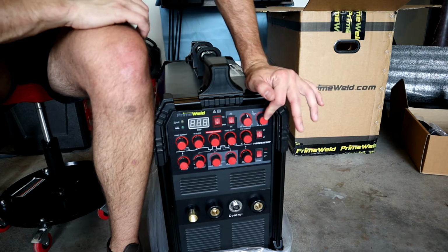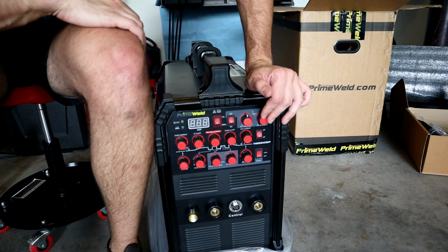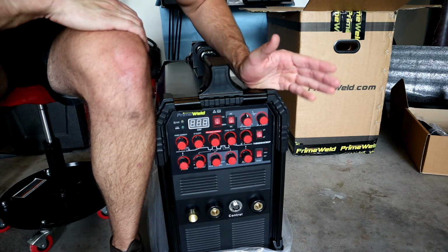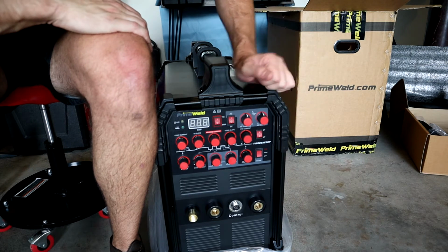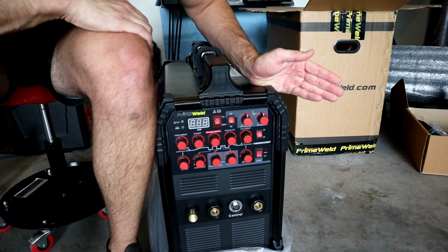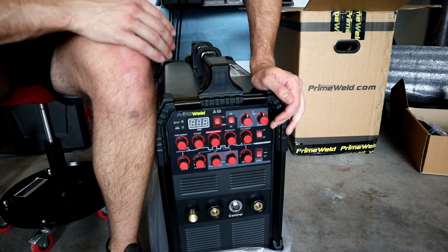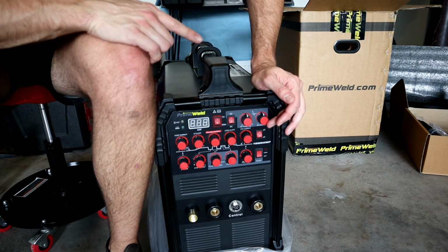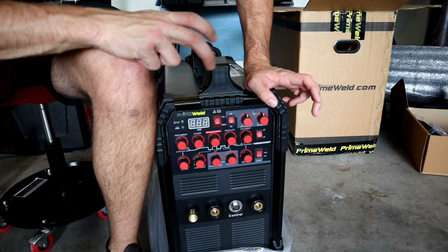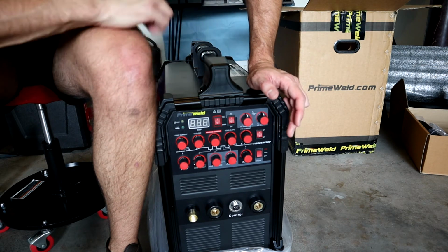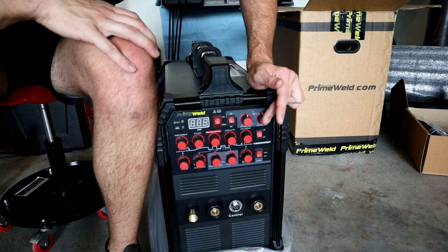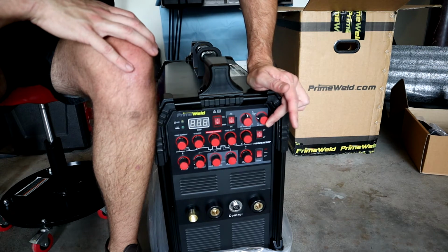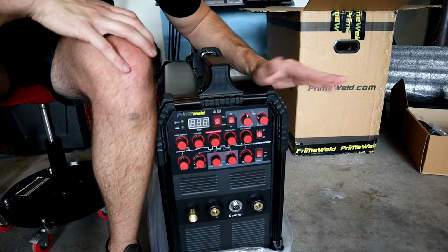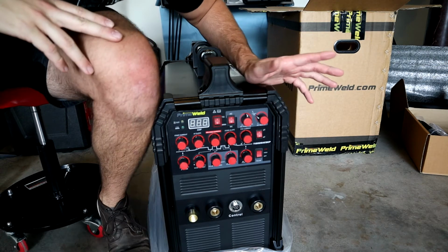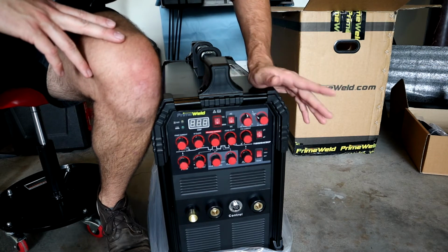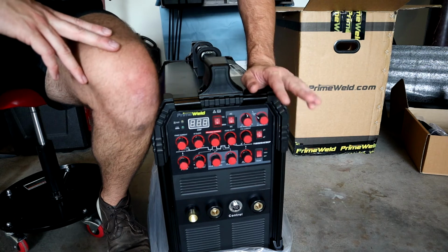Now, AC balance. There's a lot of information on AC balance, but essentially it means how much electropositive versus how much electronegative. If you have this straight up and down at 50, it's going to give you 50% electropositive and 50% electronegative. Typically when we're welding aluminum, we want the AC balance to be about 30% positive, which is also known as the cleaning action, versus the electronegative, which is the welding action. This references the positive side, so you want this balance somewhere around 25 to 30%, because that's about as much as you want when you're typically welding aluminum on AC. So to recap, 50% straight up and down is about where you want it, and really 25 to 40% AC balance is about where you want that to be.